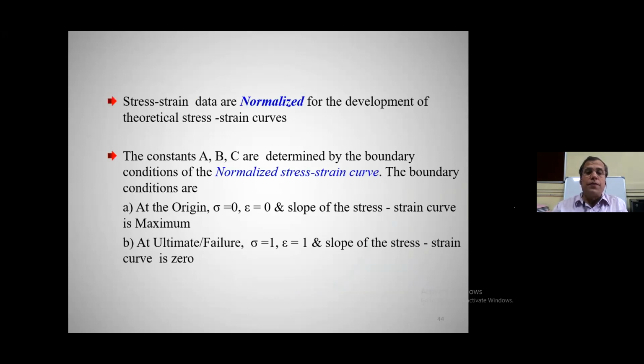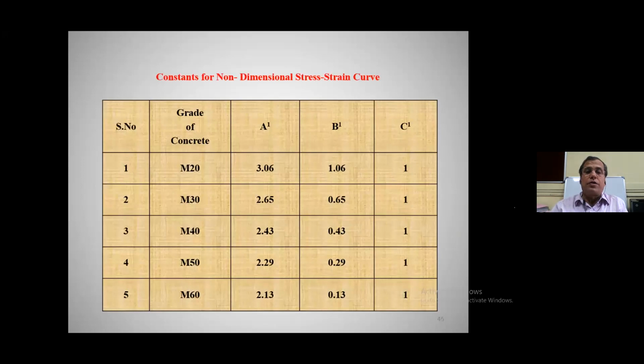As I told you, f is nothing but sigma, which is stress, and epsilon is strain. Boundary conditions have been given for ultimate 1, starting from 0.1, 0.2, 0.3, 0.4, 0.5, 0.6, 0.7, 0.8, 0.9, 1. Similarly for strain. Suppose 25 MPa has come for M20 grade concrete. The 25 MPa is normalized into 1; 90% is 0.9, 80% is 0.8, like that. Then we normalize the ultimate values for obtaining the stress block parameters. In that equation you have the constants A, B, C, and these constants are arrived at for different grades of concrete with the procedures.